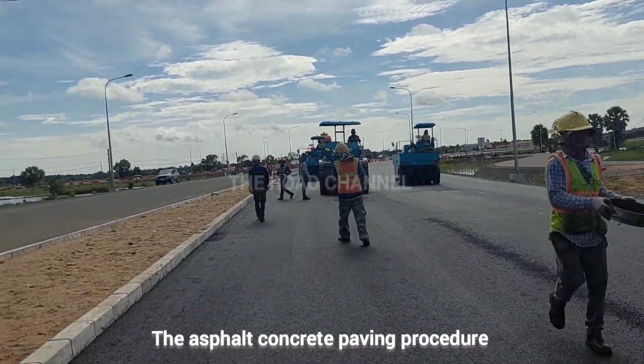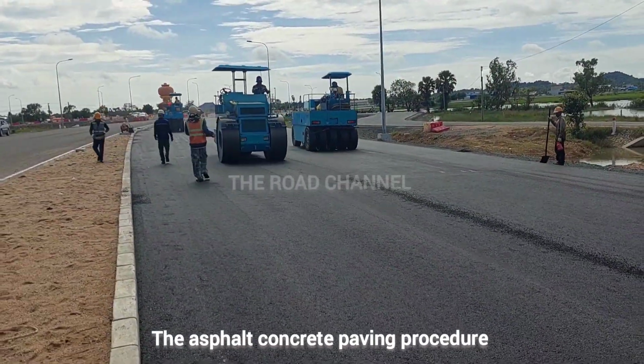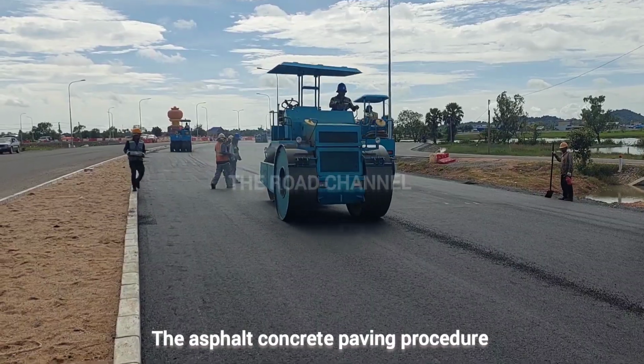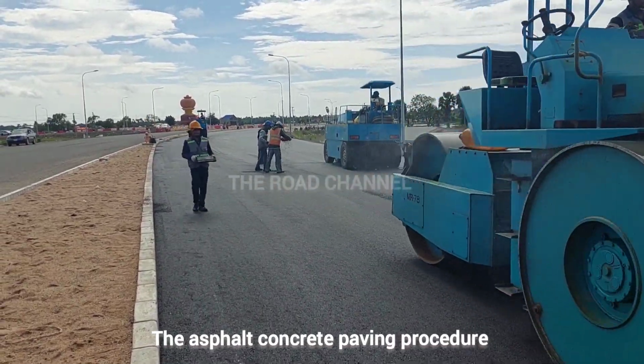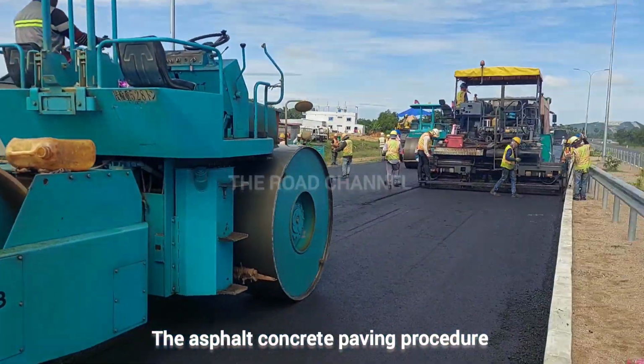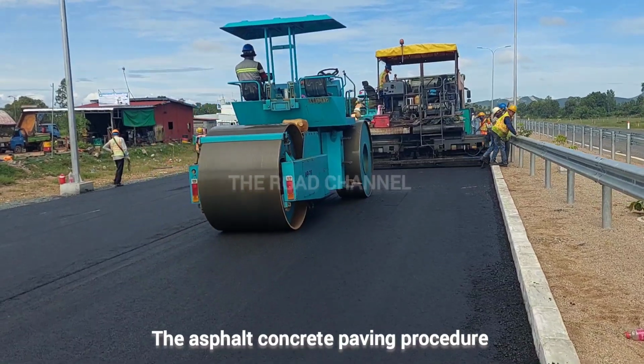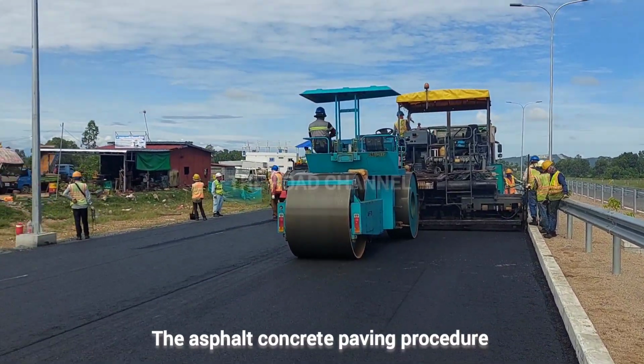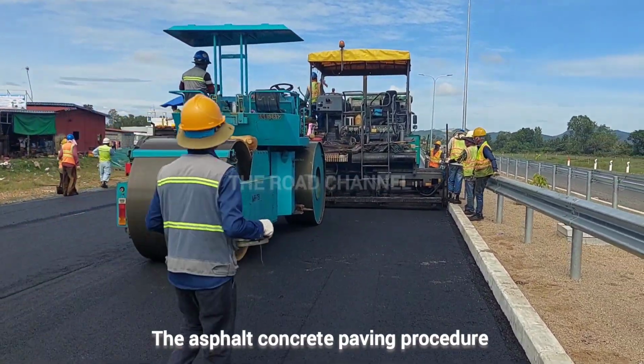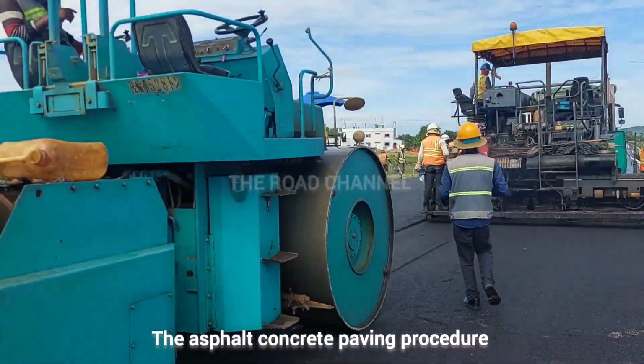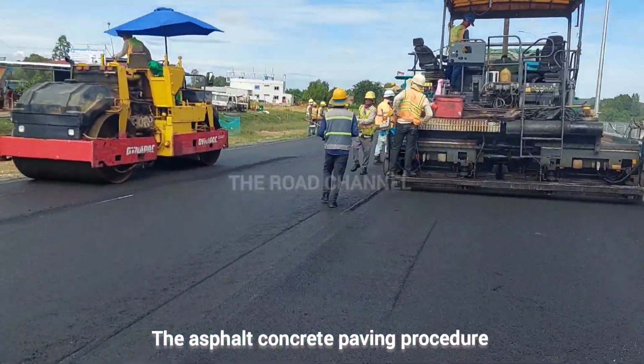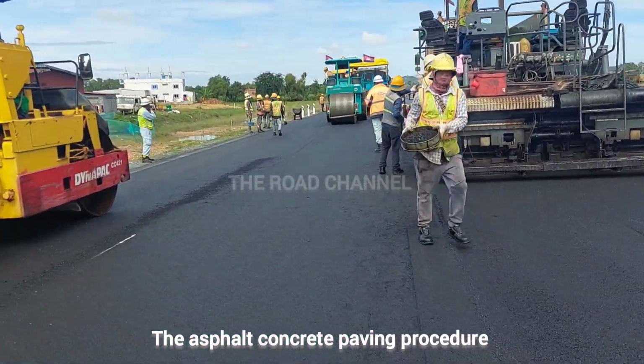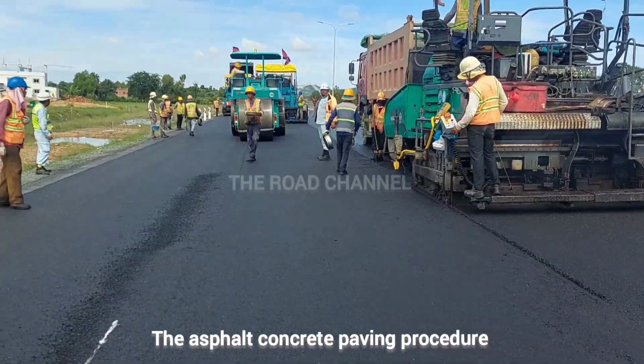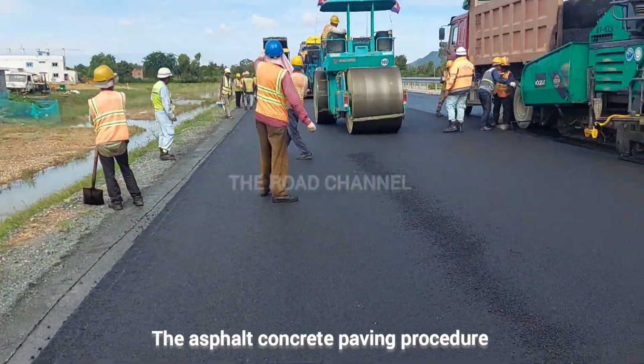3. Paving operation control. Paver machine settings. Ensure proper screed temperature and height adjustment. Verify correct paving width and thickness, typically 50 to 100 millimeters for binder course. Paving speed. Maintain a consistent speed, around 3 to 6 m/min, to avoid segregation and uneven surface.